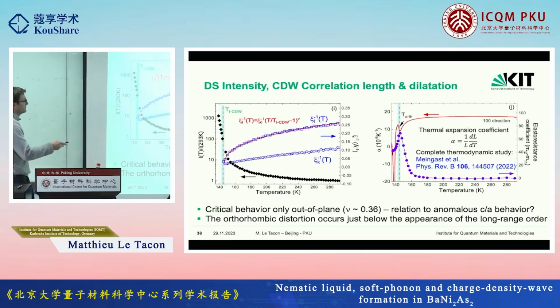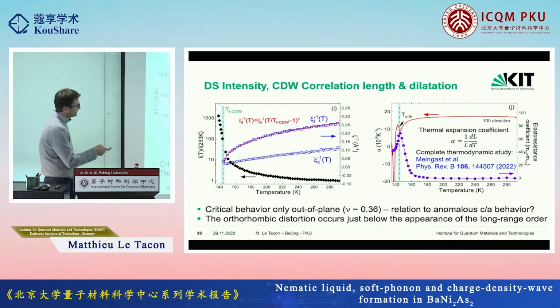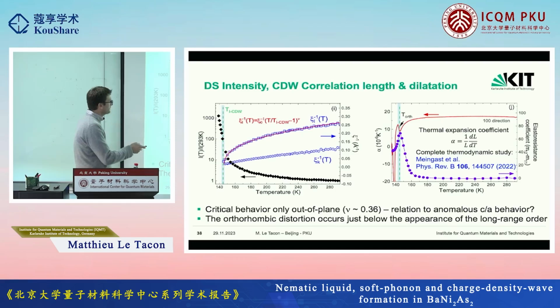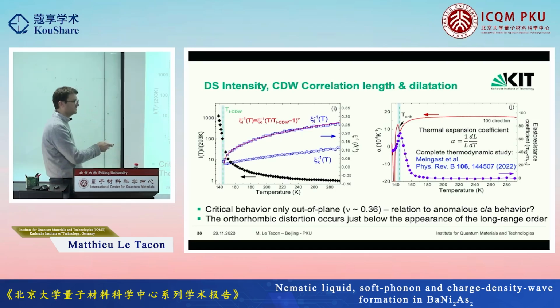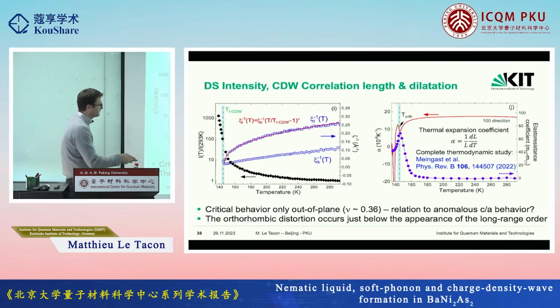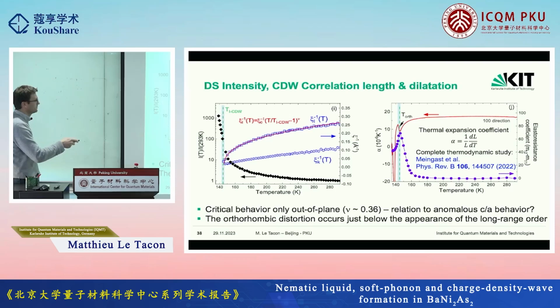So we looked at it carefully, and what we found is also quite surprising. We can look at the width of the peak, which is the inverse of the correlation length, in the plane and out of plane. And you can see that in the plane it is fairly boring. It's decreasing, so the correlation length is increasing in the plane, but nothing very specific happens. On the other hand, there seems to be some kind of critical behavior, albeit with a weird exponent, along the z-axis for the out-of-plane correlation. And that's what the intensity looks like.